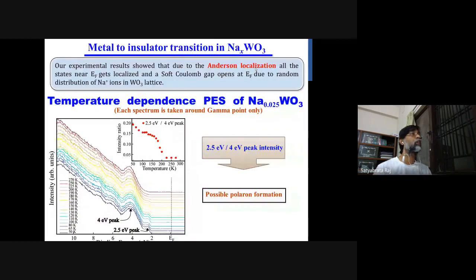So now I'll go to the temperature-dependent photoemission spectra in this insulating sample. Each spectrum is taken around the gamma point. What we thought is, let's do a series of temperatures from 50 to 270 Kelvin, because this sample is insulating, we cannot go to very low temperature, to see whether there is any new feature or not.